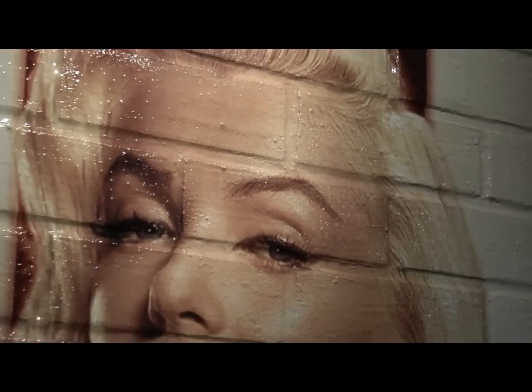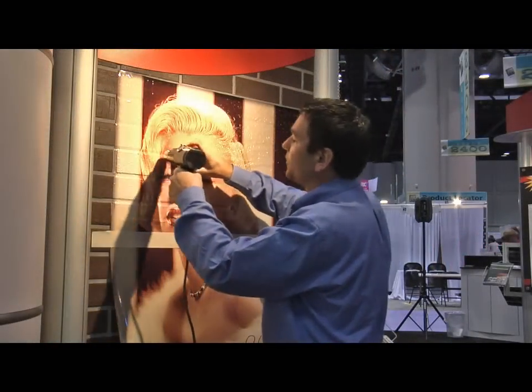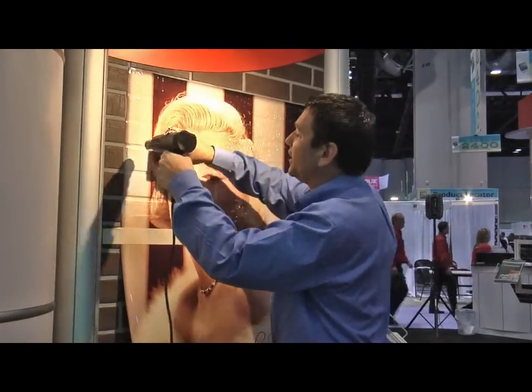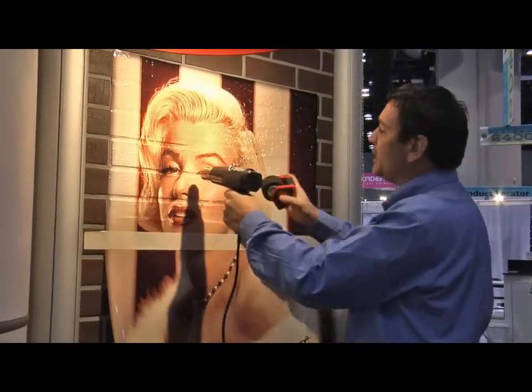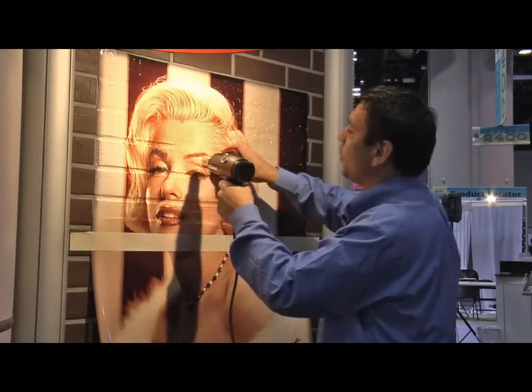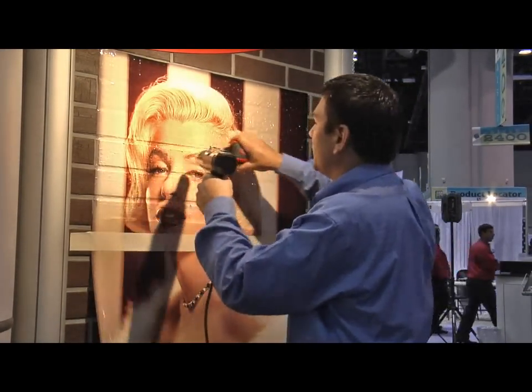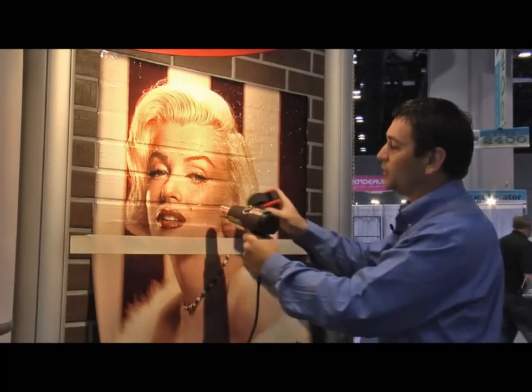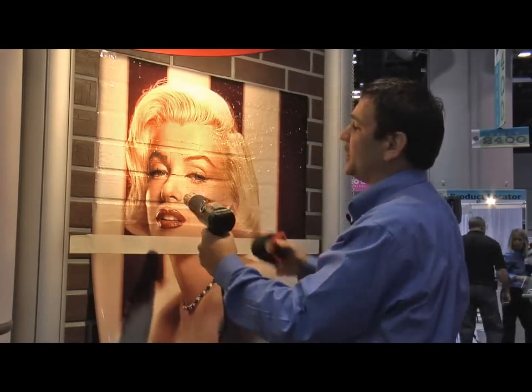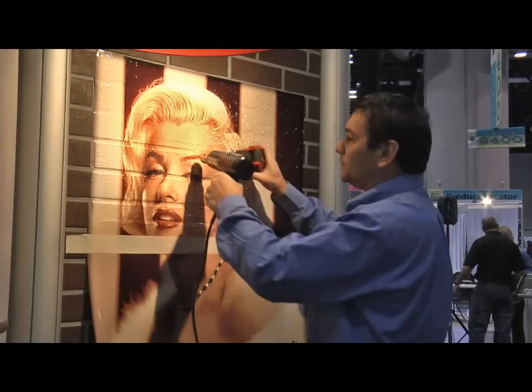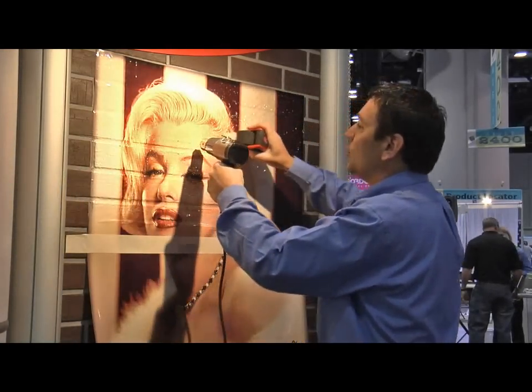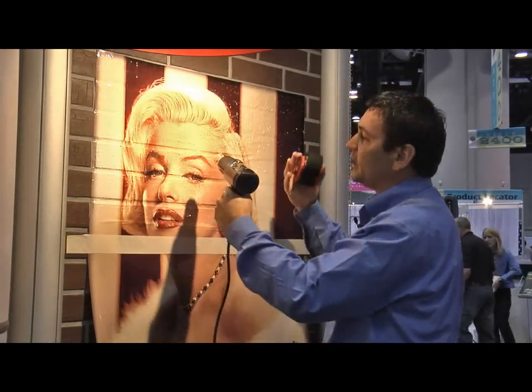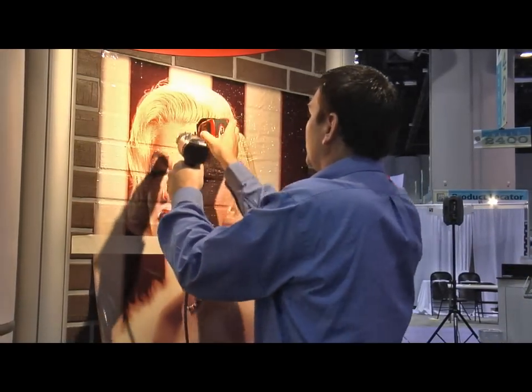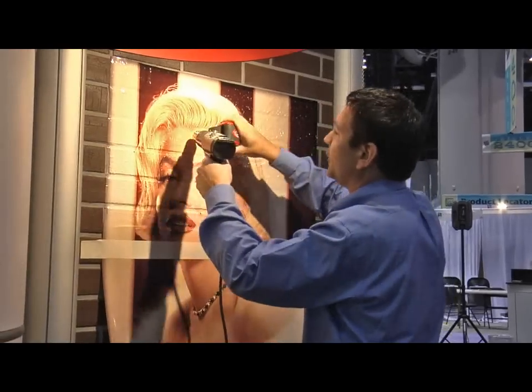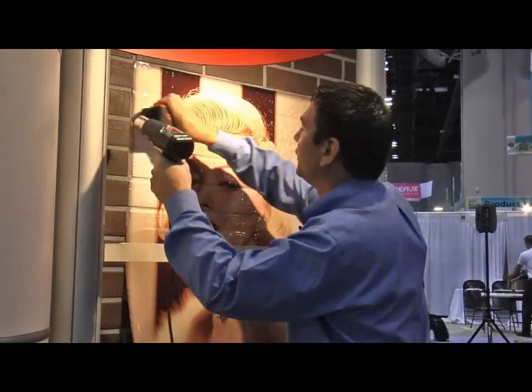Some wall graphics adhere to the textured surface by the reshaping of the vinyl. And as you can see, our wall graphic does as well. But the reason that we were able to give a longer warranty with this product than most on the market is that the adhesive is very aggressive. And the adhesive will begin over time to wick itself into the aggregate itself, making that bond permanent.